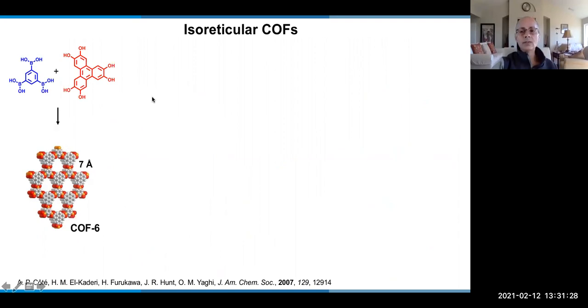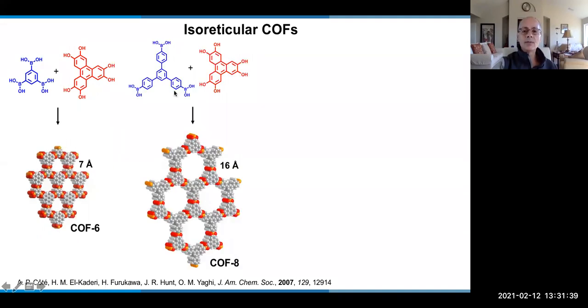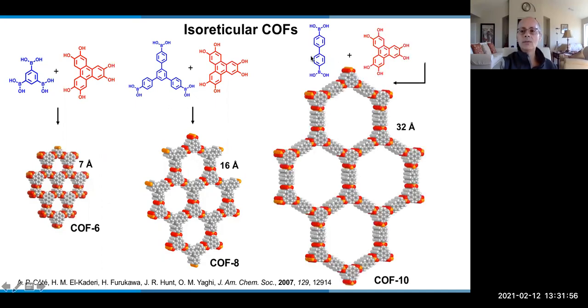Now, in reticular chemistry, one of the things that are new, of course, is that once you figure out how to make one structure, you could use the same conditions to make what we call the isoreticular form, meaning the same topology, but with either new functionality or, as in this case, new metrics. So here the pores are 7 angstroms. From this combination, you have 16 angstroms. And from this combination, you get 32 angstroms. All of these are crystalline solids, beautiful X-ray powder diffraction, and very nicely porous structures.